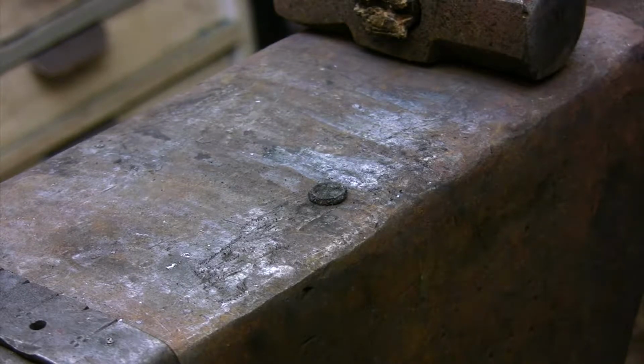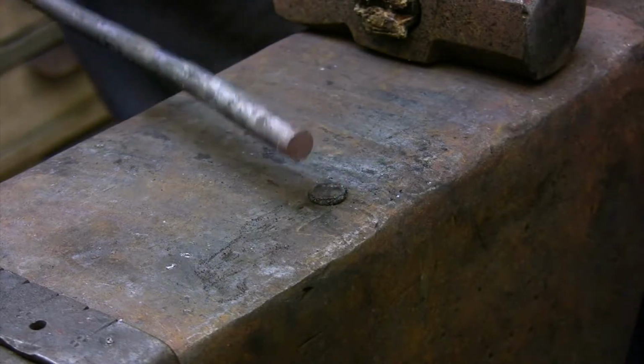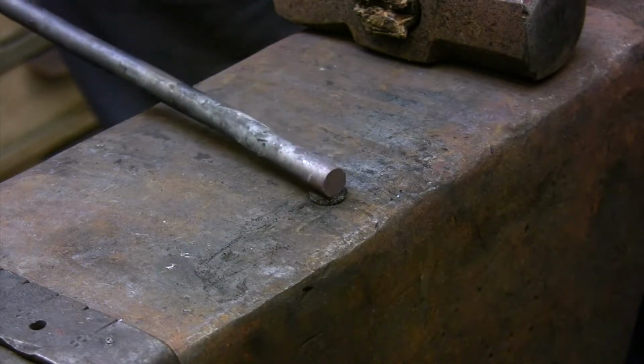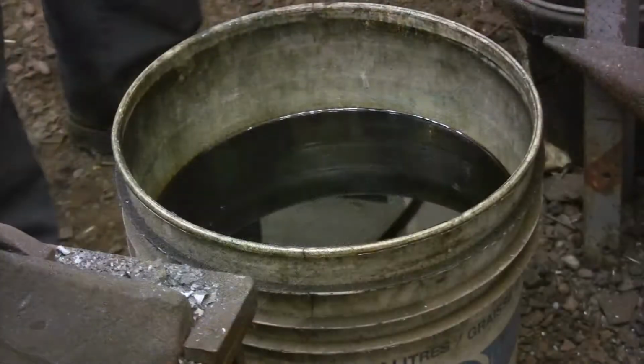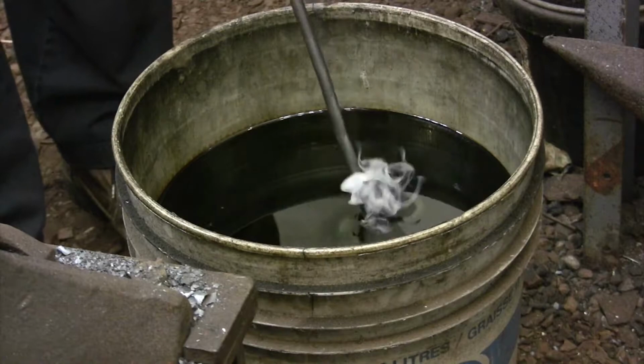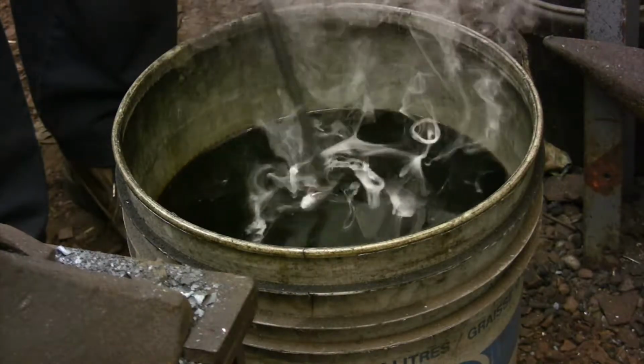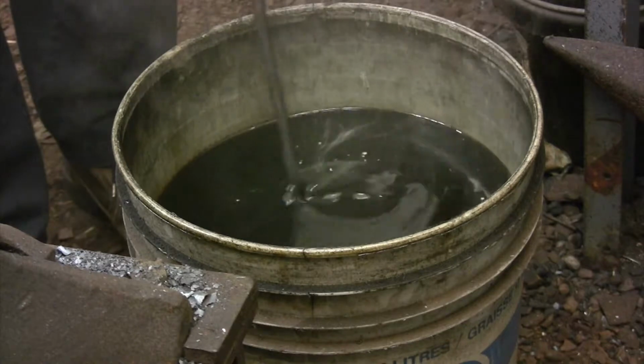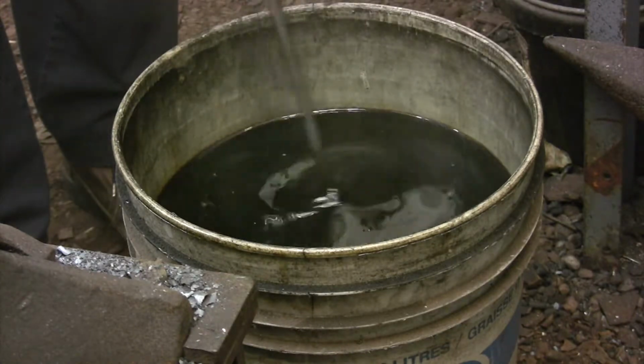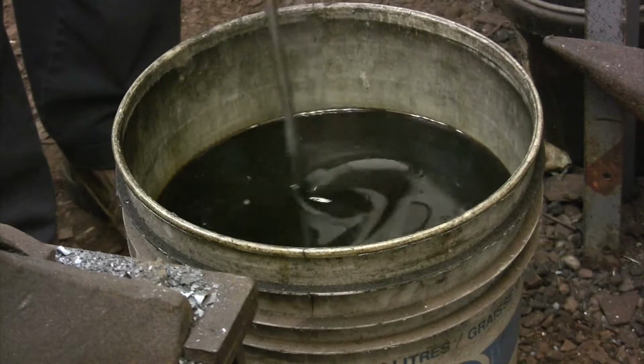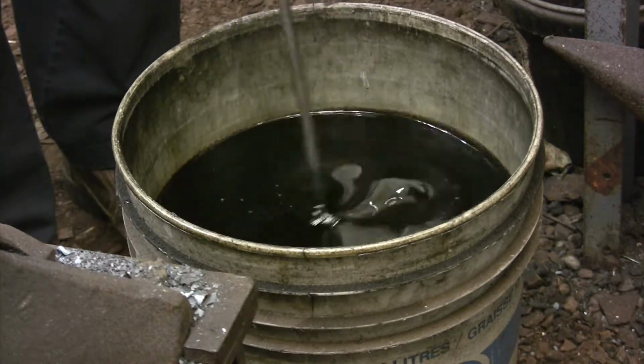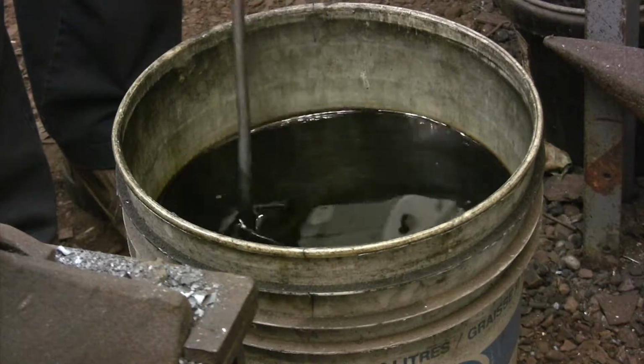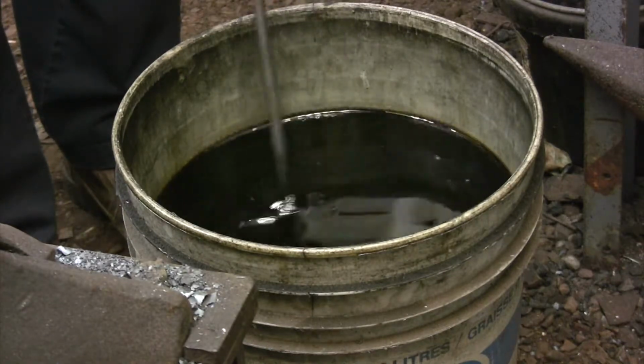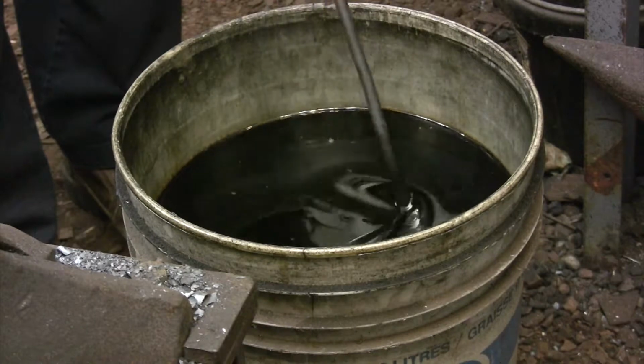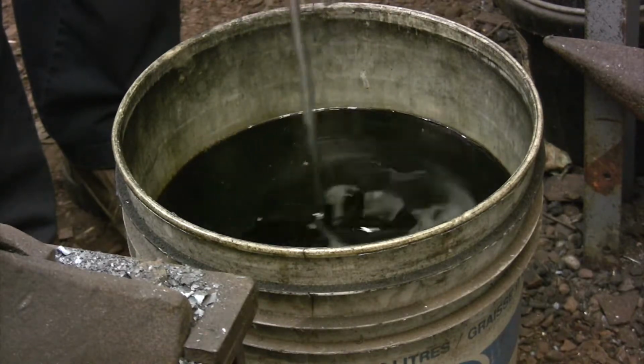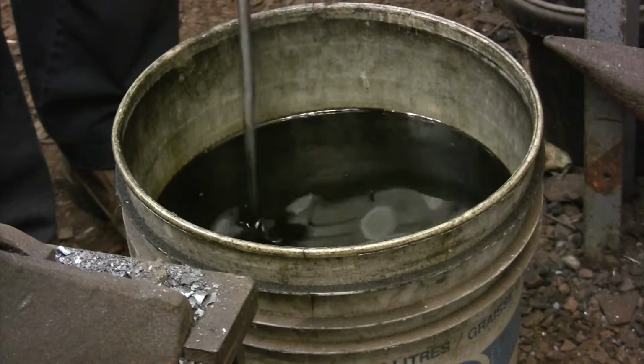The next thing you need to do is figure out what the maximum hardness is for that bar, and you do that by bringing the bar up to the critical temperature and quenching it in oil. When you're testing a bar, you always quench in oil first. If quenching it in oil doesn't fully harden the bar, then you repeat the process, and this time you quench it in water. If quenching it in water doesn't harden the bar, then you have a piece of steel that you're not going to be able to reforge and retemper in the shop. It's either a piece of mild steel or it's some kind of a specialized steel that needs some sort of elaborate process for heat treating.